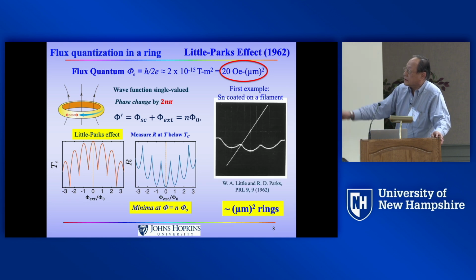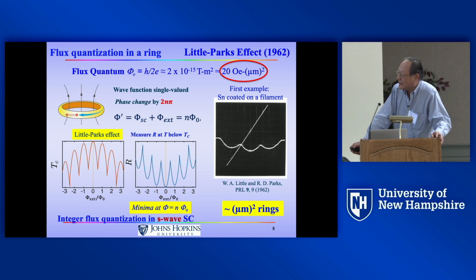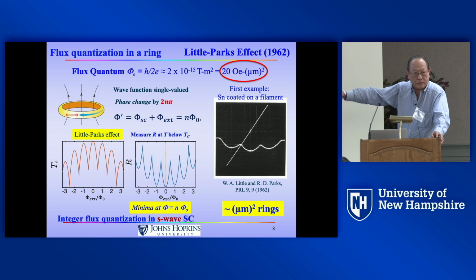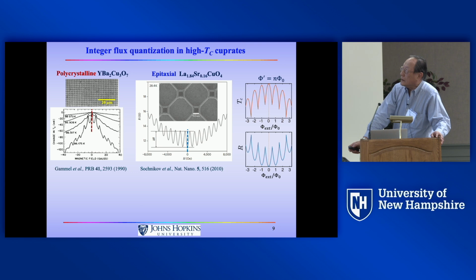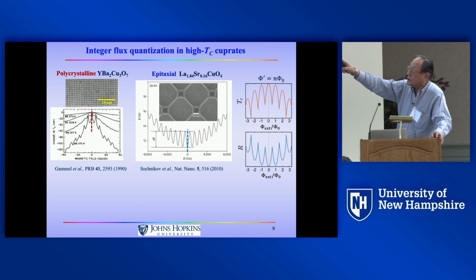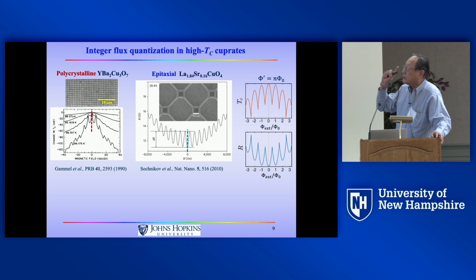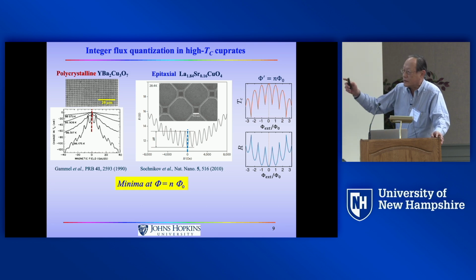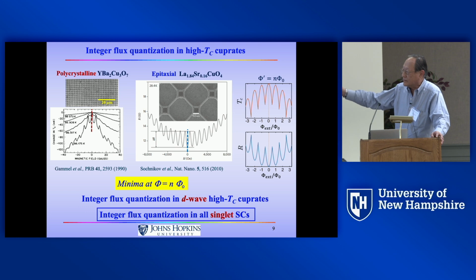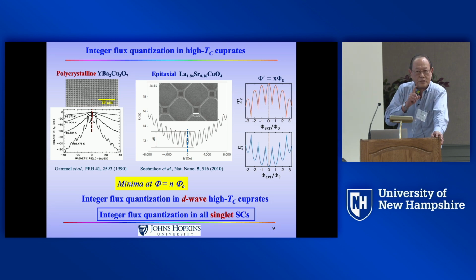Then you will see this, the first experiment. They were very clever. They did not have lithography, so they used a filament 1 micron in size, electroplated tin, and measured it. And in those days, an oscilloscope trace was good enough for a PRL, not anymore. So integer flux quanta in s-wave, they demonstrated. They actually demonstrated that Cooper pairs have charge 2e. And in subsequent years, high Tc, YBCO, polycrystalline, epitaxial, they all show integers. No exception, always integer, because in all singlets, flux quantization is always integer times phi naught.